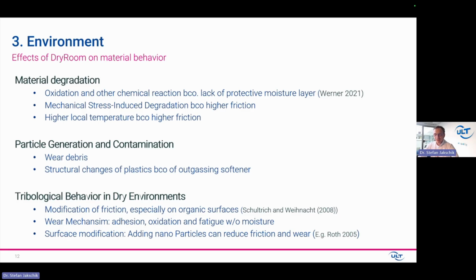Some degradation takes place because chemical reactions are made possible, since the protective moisture layer is missing. So materials wear faster than usual. And also the kind of friction and stress-induced degradation changes. So we also saw kind of debris when moving materials over one another, or just by aging effects of these kinds of materials. A lot of investigations on that one.